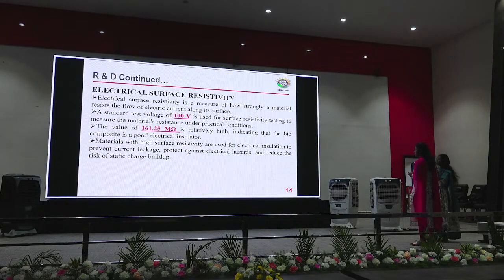Electrical surface resistivity is used to analyze how strongly our material resists the flow of electric current. We standardly test at 100 volts. As the result, we got a value of 161.25 megaohm, a relatively high resistivity range, which indicates our material is a good electrical insulator. Further, we will do an impedance tube test to confirm our acoustic property.